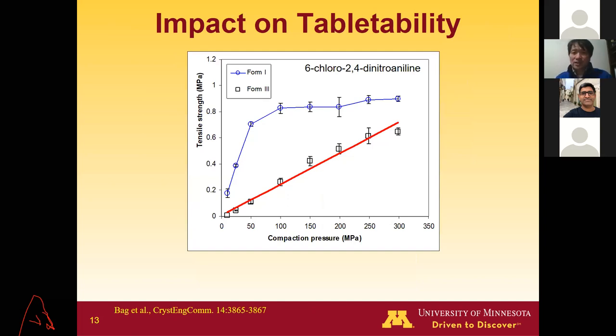When you look at this data, here's the tensile strength as a function of pressure. For both, with increasing pressure, you can make stronger tablets. So this curve increases. For form three, the harder material, it continues to increase, but in the beginning the strength is not very high. For form one, at low pressure, you can already get much stronger tablets because form one is more plastic. Therefore, the larger bonding area will be developed more easily than form three. And this strength increases